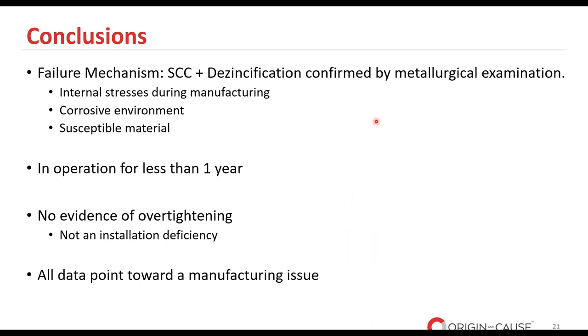And drawing our investigative journey here to a close, a clear picture begins to emerge, which paints a comprehensive understanding of a root cause or the root causes behind the failure. The primary diagnosis here, backed by a rigorous metallurgical examination, points toward the combined effect of stress corrosion cracking and dezincification. These mechanisms, when combined, can be particularly devastating. And zooming into the causative factors, the three primary culprits that were identified were the internal stresses, the corrosive environment, and the inherent vulnerability or susceptibility of the material that was used. And it's noteworthy that despite being in operation for less than 1 year, this level of degradation occurred. So this accelerated type of failure underscores the inherent issues.